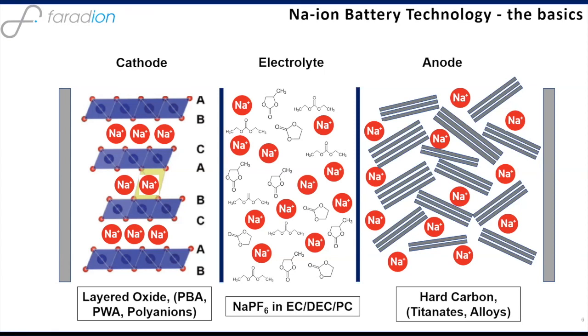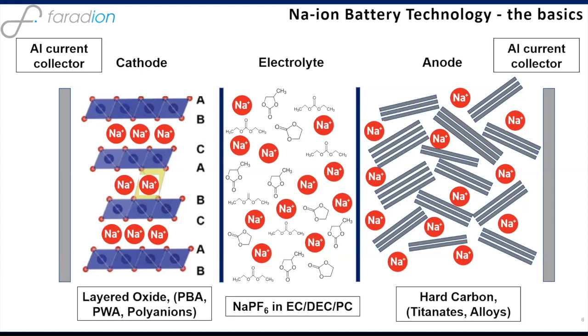The electrolyte is analogous to what you'd use in the lithium space. From a commercial standpoint, most companies are using NaPF6, the sodium version of obviously LiPF6, in a mixture of cyclic and aliphatic carbonates. I make the point here that one of those cyclic carbonates that you can use is propylene carbonate. Can't use that in the lithium space because of the exfoliation problem with graphite, but that gives you a lower volatility electrolyte and better liquid range. And just to remind you again that we use aluminium current collectors on both sides of the cell.